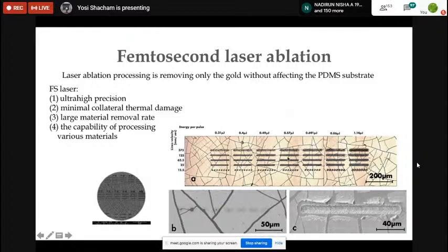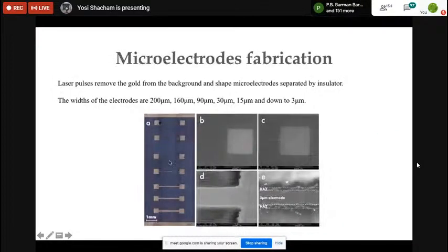And by the way, you can see here that we use the monomer and the PDMS with a relatively high CTE, so we got cracks. But the good news is that even though we have cracks, all the devices worked, because the cracks are only in the gold on top of the PDMS. The gold inside the PDMS is still conducting. This is top view, this is the cross section. And this is how it looks.